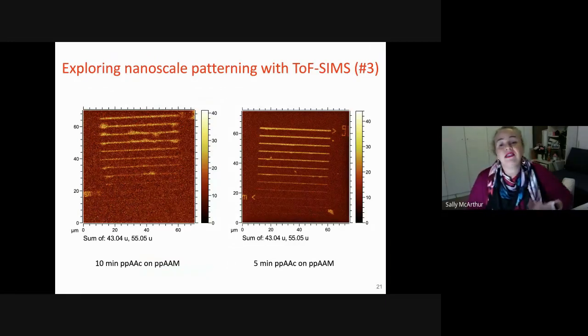And so that's again where TOF-SIMS comes into play. The interesting thing for us is that this is right at the boundary of where your traditional TOF-SIMS instrument works. The spatial resolution of TOF-SIMS typically is quoted at the 100 nanometer level for inorganic materials. For organic materials, we have a lot more trouble. But there's sort of a dual thing here of actually pushing the boundaries of the spatial resolution that we can get out of the TOF-SIMS imaging and the scale of the patterns that we've got.